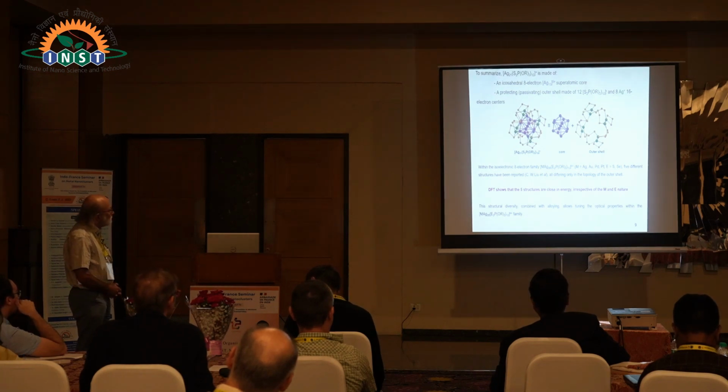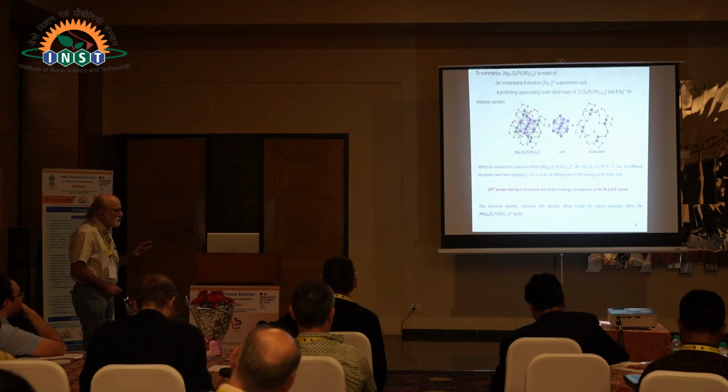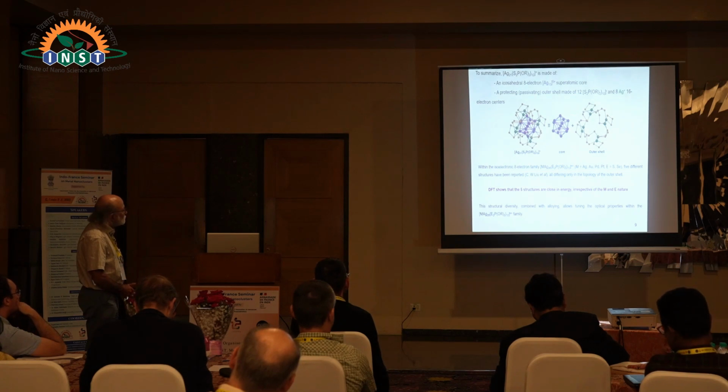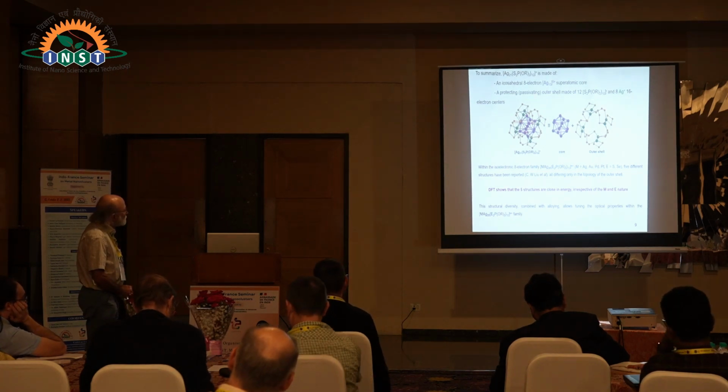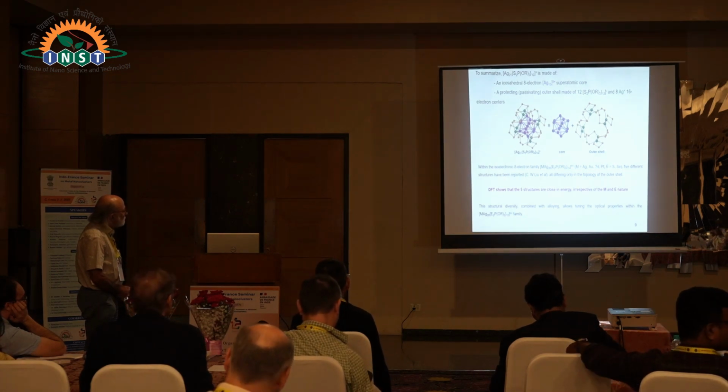And actually, their bonding with the pink atoms is mainly metallophilic in character. The covalent character is very weak. And it turns out that it's possible to alloy these systems and change the metal in the center by gold, platinum, palladium.